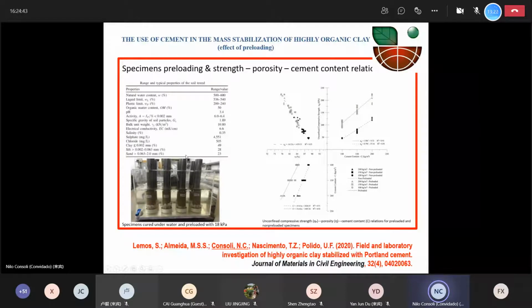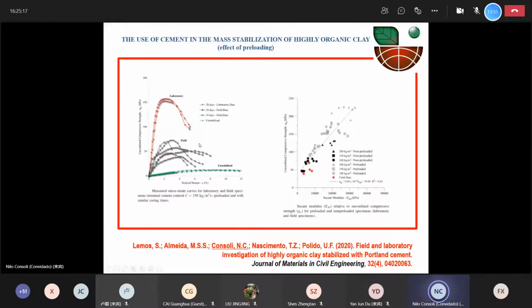What we realized was that using 3 different amounts of cement, 100, 150, and 200 kilos per cubic meter, without any surcharge, and with a surcharge of 18 kilopascals, in the end we can get a unique curve between porosity and unconfined compressive strength of these specimens. This is all published in this paper from last year in the Journal of Materials in Civil Engineering from ASCE. Here we also have some results of this unconfined compressive test, but also the stress strain curve